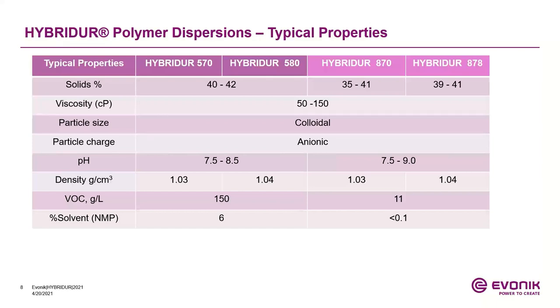The Hybridur polymer dispersions, these are the typical properties. For the 570 and 580, there's 40 to 42% solids. The 870 and 878 are somewhere between 35 to 41% solids. And they're both colloidal in terms of particle size. The particle charge is anionic, and these polymers do not have any surfactants in them. With a pH of somewhere between 7.5 and 9, the 570 and 580, because those are the NMP versions, are 150 grams per liter VOC, and 870 and 878 are just 11 grams per liter VOC. There is 6% NMP in 570 and 580, and Hybridur 870 and 878 are basically NMP-free.